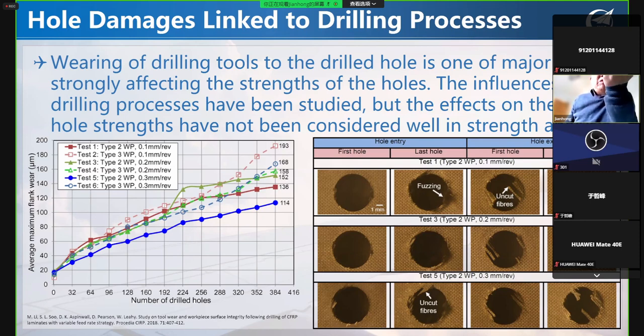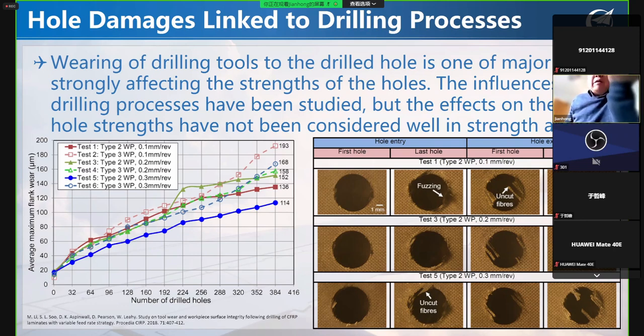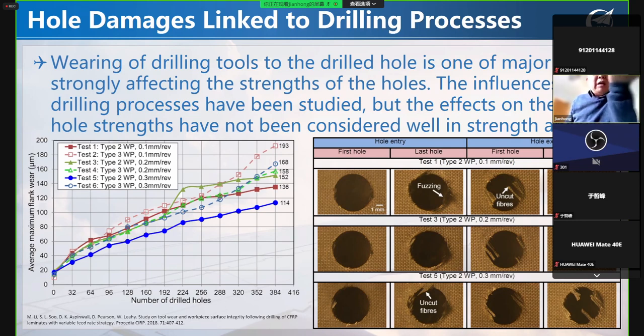This is why the drilling process is strongly linked to open hole machining damage. More than ten years ago, I made a cooperation with the University of Bristol and tried to conduct a virtual test to predict open hole tension failure — the accuracy was roughly about 70%, and the remaining 30% could not be captured properly. Additionally, the wearing of tools causes more differences in hole machining, since using the same drill for different holes means the damage content degrades differently. When the drill is very sharp, hole quality is good and damage is less, but at the end of the drill life, there are a lot of defects in the open hole.